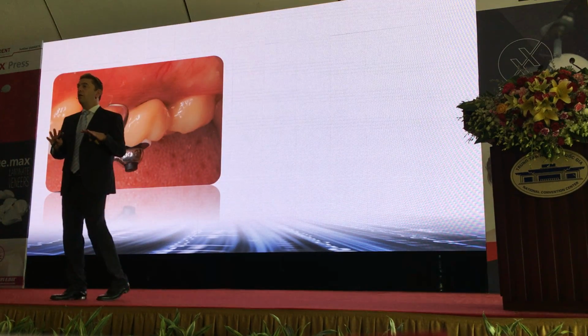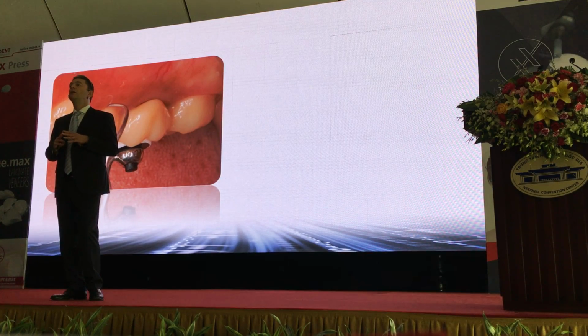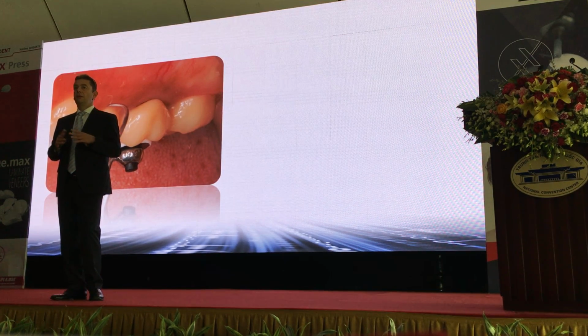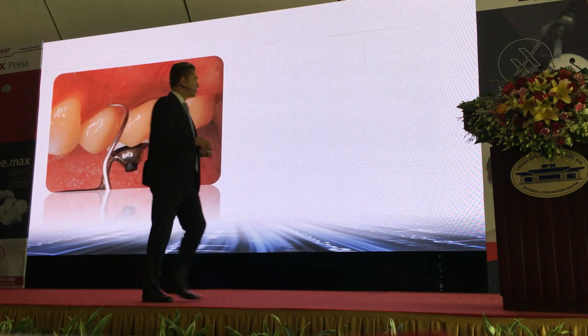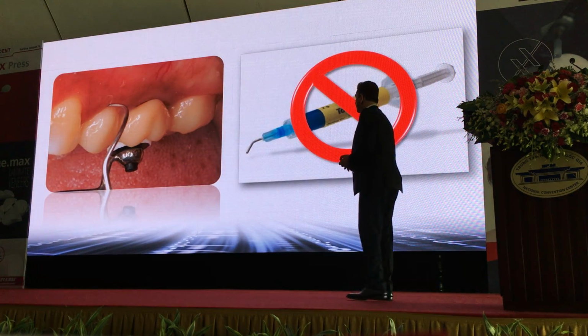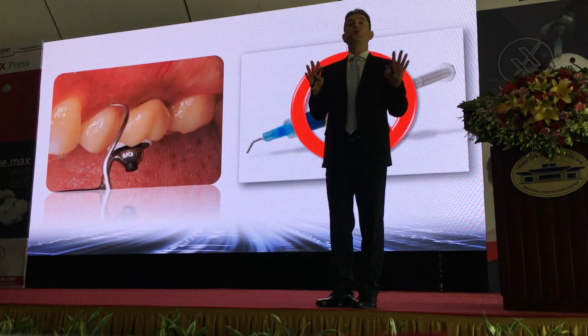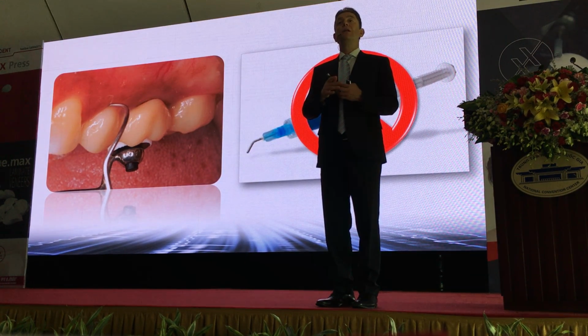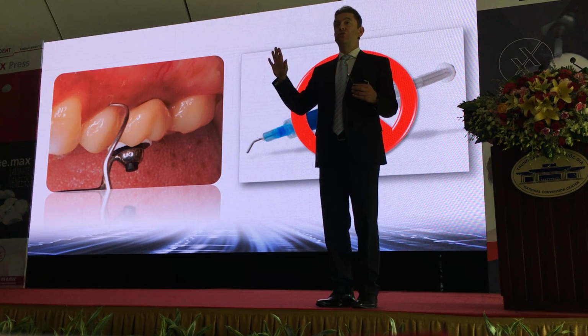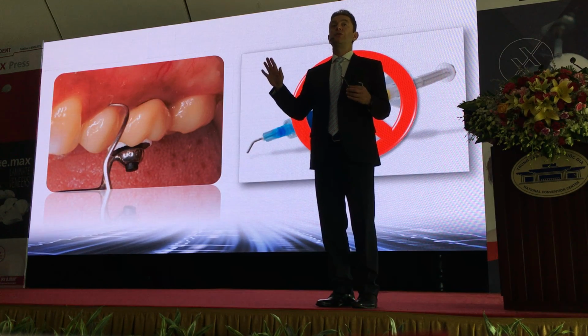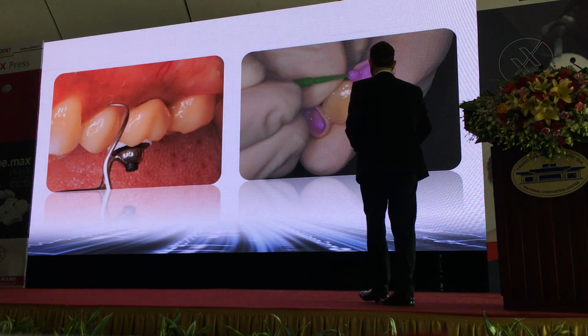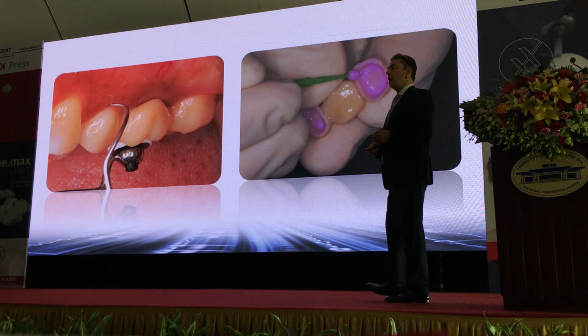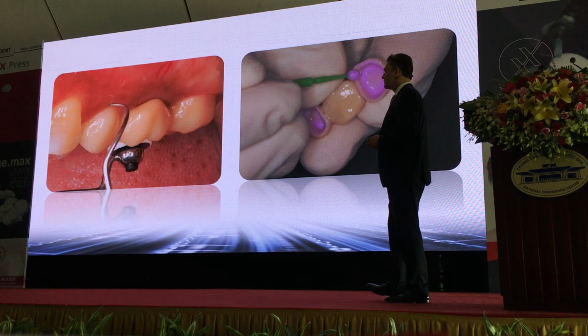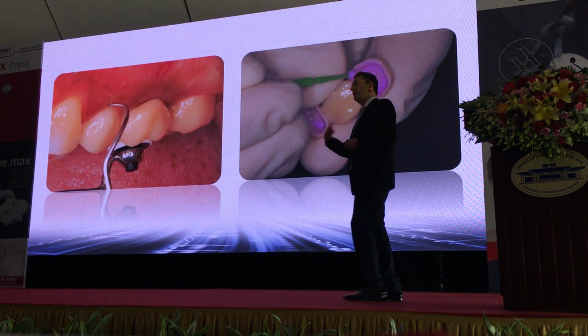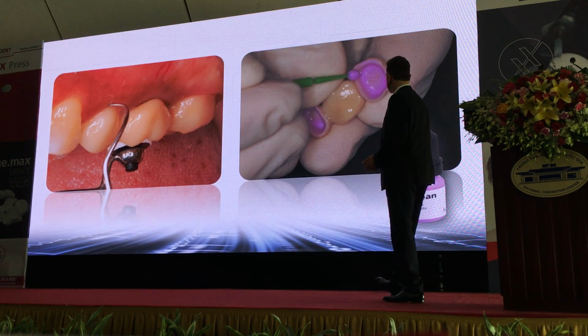So during the try-in of your sandblasted zirconia, you will have contamination, right? Even if you isolate, you have some sort of contamination, and the contamination is a problem. So how do you get rid of contamination? Don't use phosphoric acid, because phosphoric acid will block the adhesion to the zirconia. So it's not good to use phosphoric acid on zirconia for cleaning. It's much better to use IvoClean. I will explain in a little more detail how this works, but with IvoClean, you just apply it for 20 seconds, rinse it off, and then you have a clean surface that you can bond to.